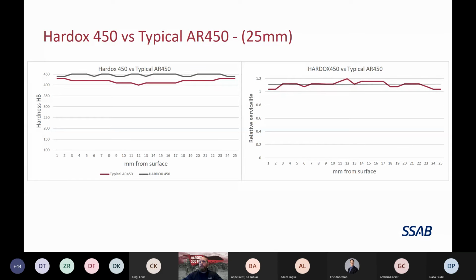So this is a chart showing Hardox 450 versus a typical AR. The Hardox 450 on the left chart is the gray line up at the top, and it's basically the hardness through the thickness of the plate. The red line shows a competitive plate. The chart on the right shows the relative service life. Because there's a difference between the two plates on hardness, especially through the center of the plate, for a 25 millimeter plate we can see approximately a 10% increase in relative service life just switching from a typical AR 450 to a Hardox 450.